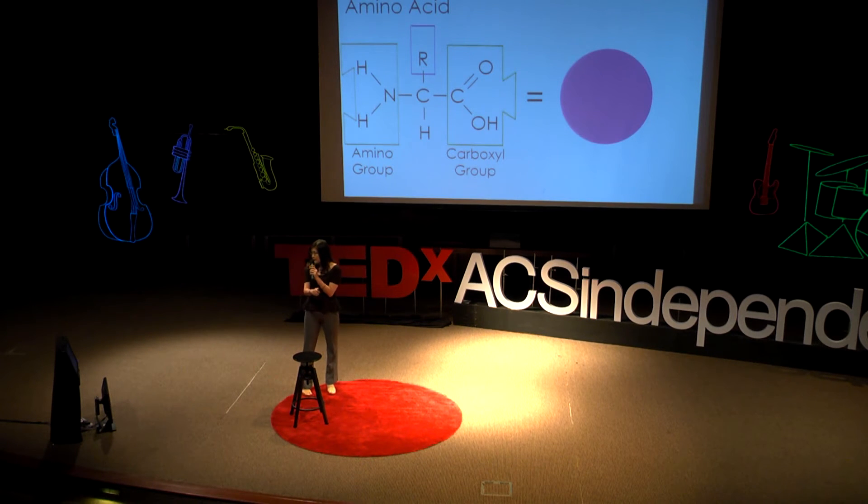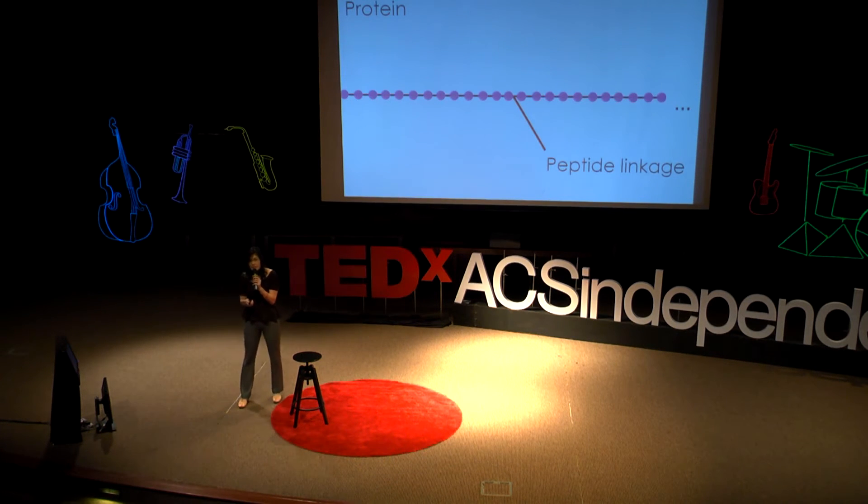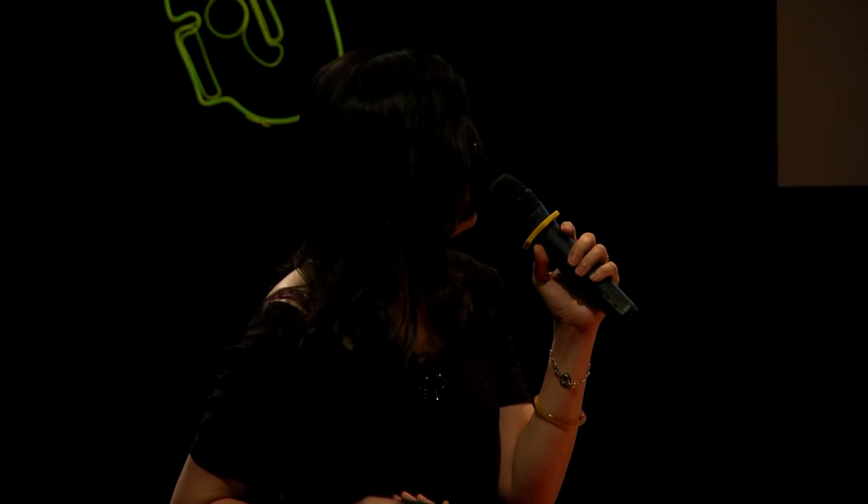You can see this is an amino acid with an amino group and a carboxyl group. If you put so many of these repeat units together, you will have a long chain protein or polypeptide — basically, you have peptide chains. But it's not so simple for our hair because hair is very, very strong. So you need some special structure — a little bit crystalline and also a little bit amorphous, and it has to be very long. Therefore, the hair from Mother Nature is in a helical shape, and this helical shape is held firmly together by cross-linking bonds like disulfide bonds and hydrogen bonding, as well as intermolecular bonding against the adjacent amino acids. So this is a very firm structure and very, very strong in tensile strength.